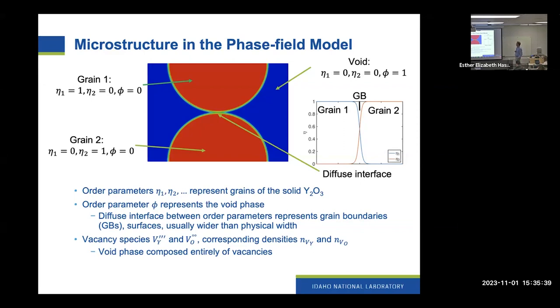We have an order parameter representing each grain, and the order parameter has the value of one in that grain, and all the other parameters have a value of zero. Grain two is something similar. And then, rather than a fission gas bubble here, we have a void, and we have an order parameter representing that void. The test case material that we're using here is yttria. It has a defect structure that's relatively similar to UO2, but doesn't present so many of the challenges to work with experimentally. So that's why yttria is our test case.